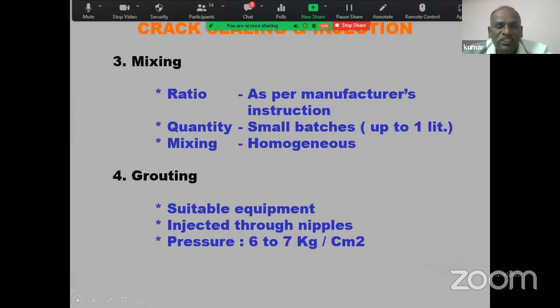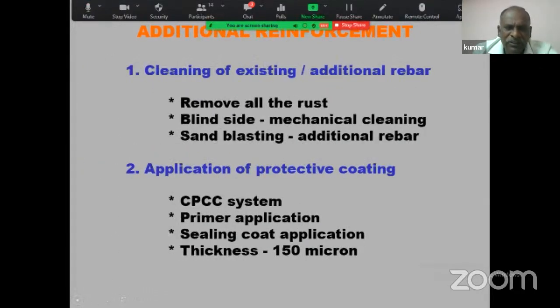Now this has to be mixed properly. The ratio is as per the manufacturer; we take a small quantity and inject it. The mixing should be homogeneous. For grouting, we have to use proper equipment and inject through the nipples. The pressure is 6 to 7 kg per centimeter square, so it will go inside. That is the way you can make a grout injection of the cracks.